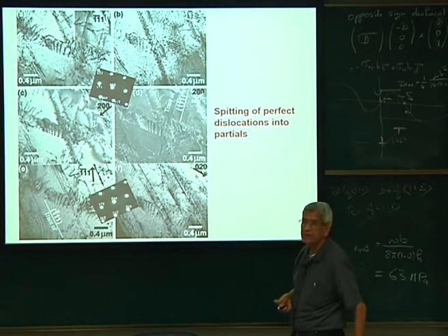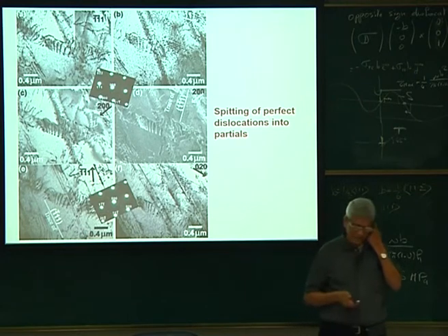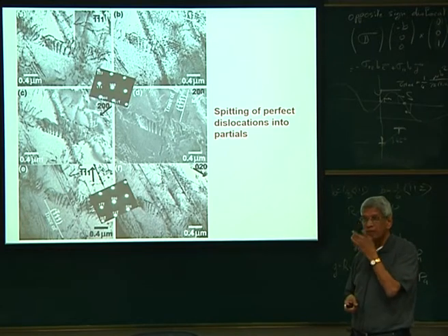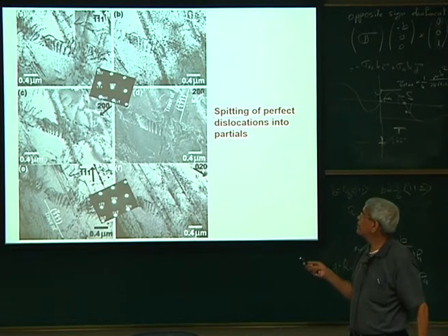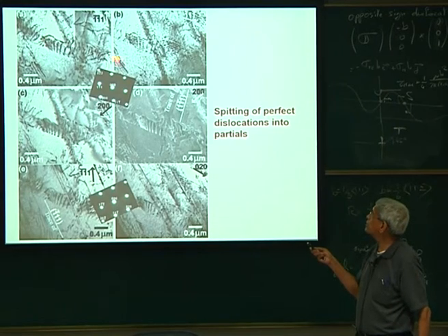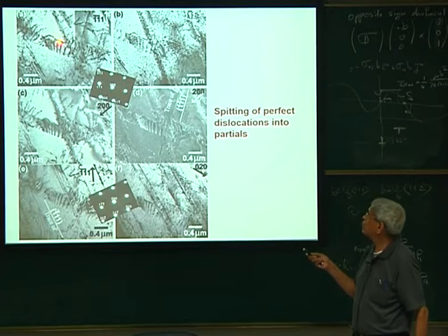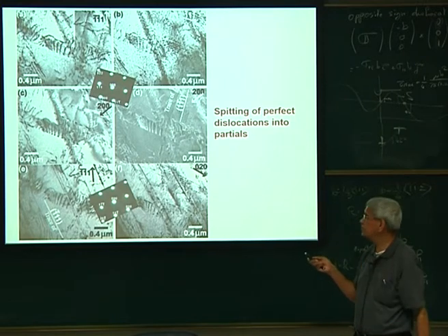This one which I have taken is a nickel based superalloy which contains fine precipitates, where the stacking fault energy of the material as well as the precipitate is low. When the dislocations pass through the sample, one partial could be seen, then the fringe could be seen, and the other partials are not visible. With different conditions when I try to image, different faults could be seen.